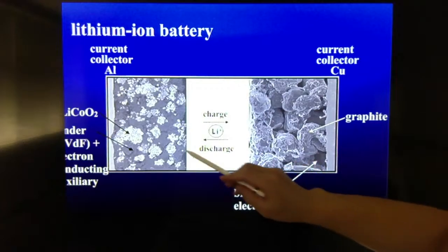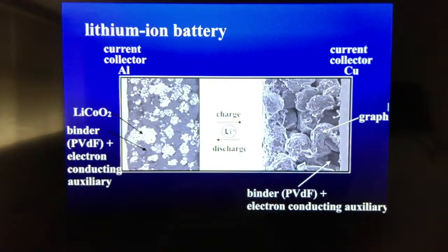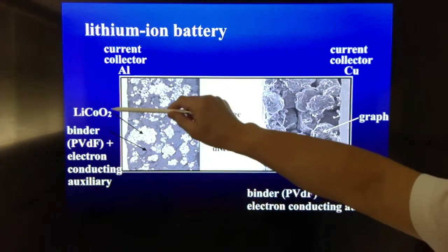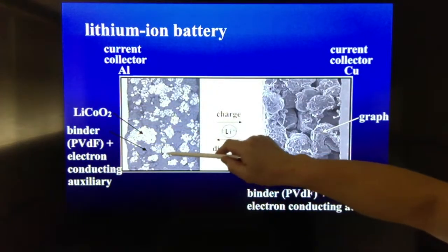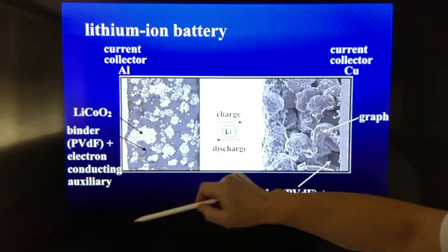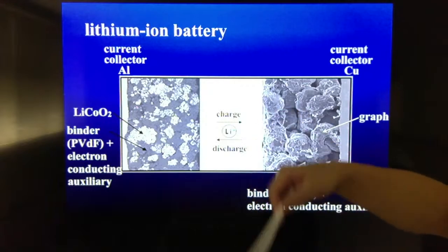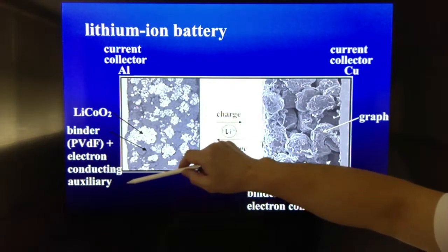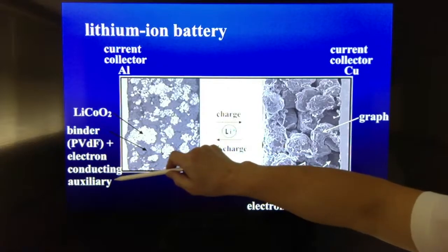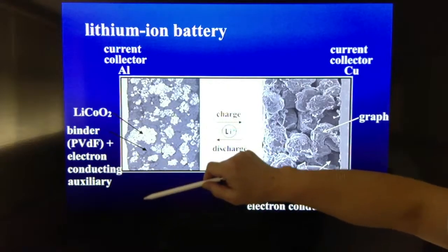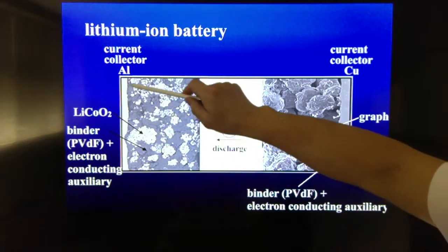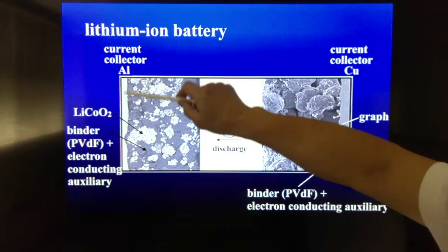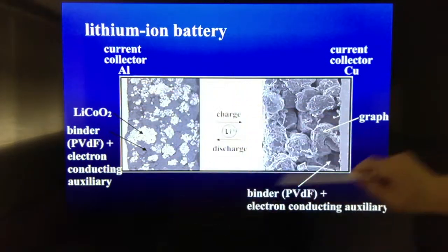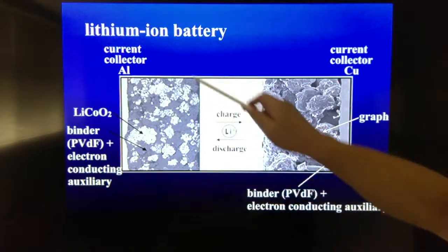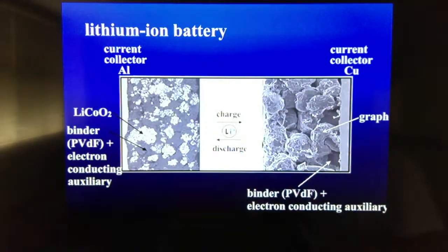And this is the electrolyte, and the cathode is almost the same story. Not only the cathode material, cobalt oxide, you need a binder to immobilize this stuff, and also a conducting accessory to get smooth electron conductivity. And finally, you collect the electron at the aluminum foil here. This side aluminum foil and this side copper. So those electrodes have quite a composite and complicated structure.